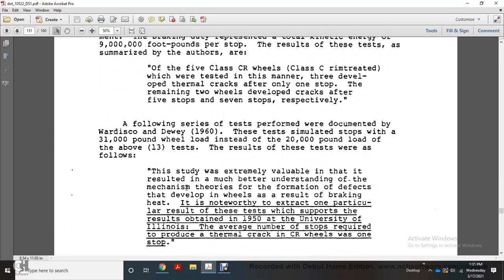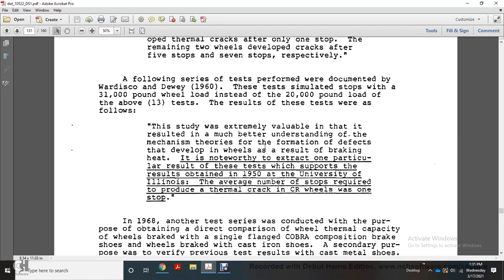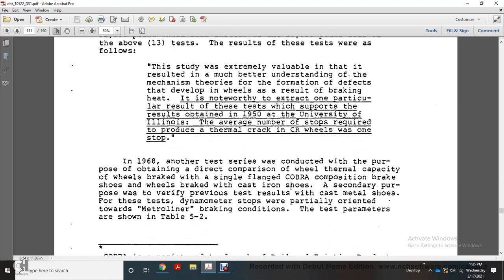Following series of tests performed, the test stipulated stops with a 31,000 pound wheel load instead of a 20,000 pound wheel load. The results of the test were as follows. These studies are extremely valuable in that they resulted in a much better understanding of the mechanism and theories of the formation of the defects developing in wheels and resulting from braking. It is noteworthy to extract from the results of these tests reported in 1950 by the University of Illinois that the stops required to produce thermal cracking of Class C wheels was one stop.